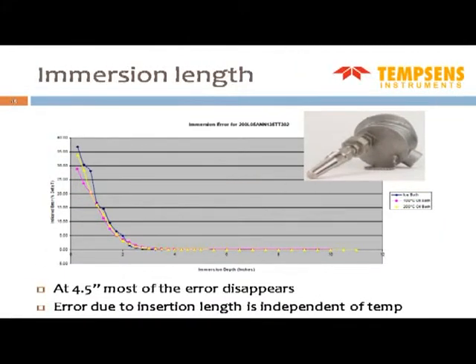For example, we have here a sensor which is at different temperatures. The blue one we can see is for ice at 0 degree centigrade. Then the pink one is at 100, and the yellow one is at 200. We have done it in a calibration bath, and you can see the error. It is almost more than 4 inches for this dimension. 4 inches is about 115 to 120 mm. Beyond that we are able to get the right kind of accuracy.